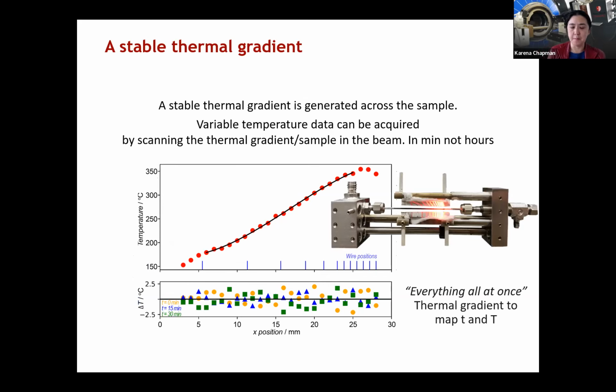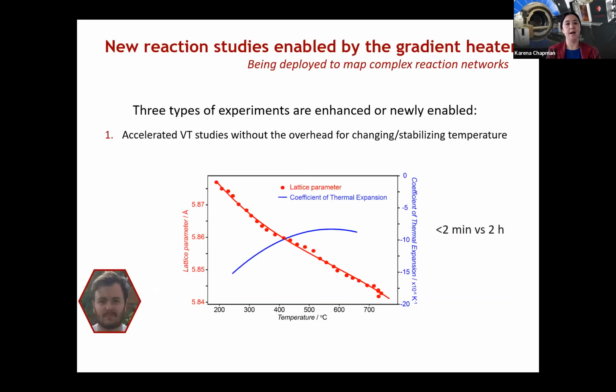We can start to consider looking at multiple temperatures in parallel by generating a thermal gradient across the sample. So one side of the sample could be sitting at 350 degrees, and the other side at 150 degrees. By moving the sample in the X-ray beam, we can look at different temperature points as a function of time, and monitor the reaction progress at multiple temperatures in parallel using a thermal gradient.